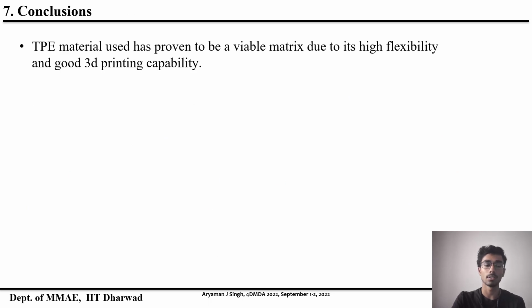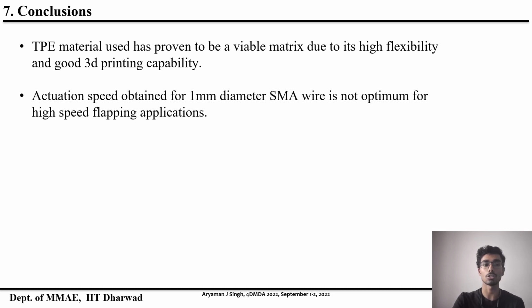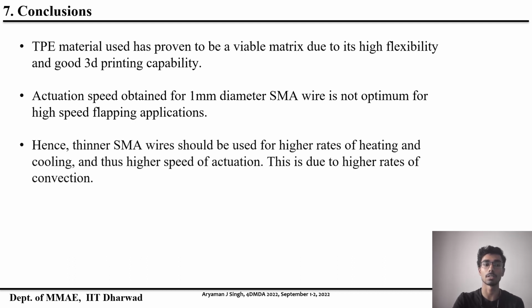To conclude, the thermoplastic elastomer material used has proven to be a viable matrix due to its high flexibility and good 3D printing capability. Actuation speed obtained for 1 mm diameter SMA wire is not optimum for high-speed flapping applications. Hence, thinner SMA wires should be used for higher rates of heating and cooling and thus higher speed of actuation. This is due to higher rates of convection.